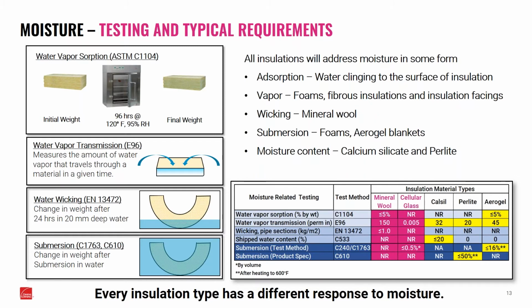One of them is water vapor sorption. This is how much water actually clings to the surface of the insulating material. And this is typically done with things like mineral wool, fiberglass, and aerogel blankets. Basically, we take the product, we put it in a humidity cabinet with high temperature and high humidity for 96 hours, and then we weigh it once it comes out. Generally speaking, those numbers are pretty small for the products that are tested. For fibrous materials, it's going to be less than 5% by weight.